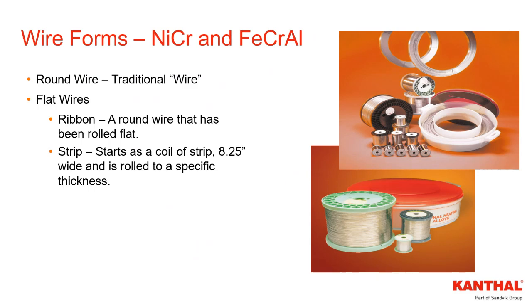And then you have strip, which starts as a coiled strip, so basically a flat rectangular piece of material that could then be rolled and flattened to get a specific thickness. So it's just important to note that the edges are square and sharp, so they're not rounded like a ribbon material. I wanted to point these different wire forms out because typically different styles of heating elements will perform better using one specific alloy shape or another. So, for example, traditionally round wire is used with a coiled heating element. It's not always the case, but it's typically the case.